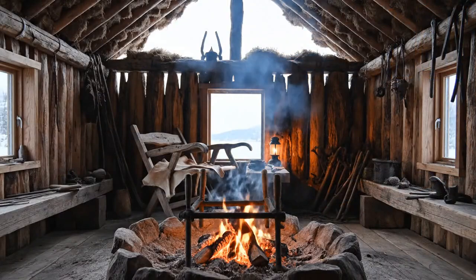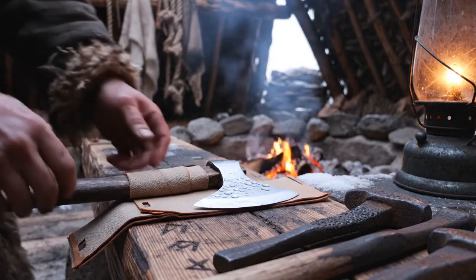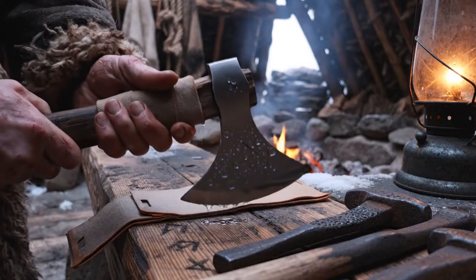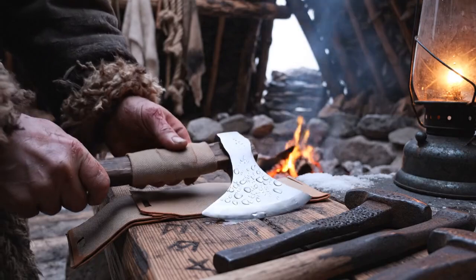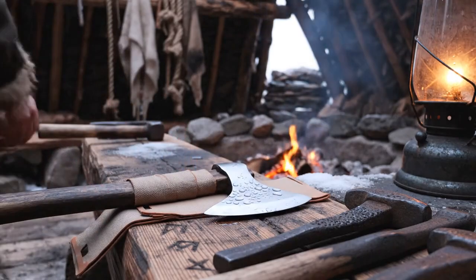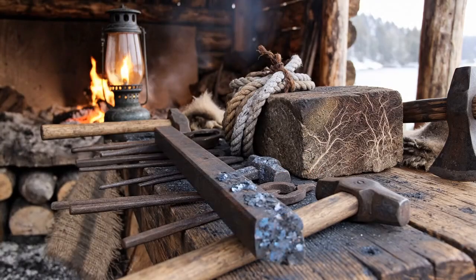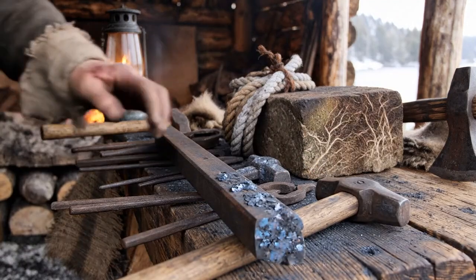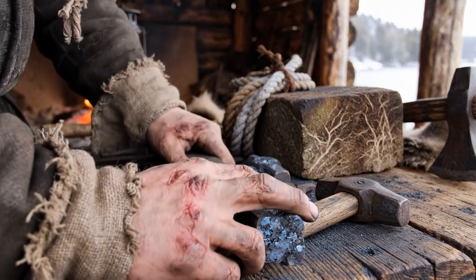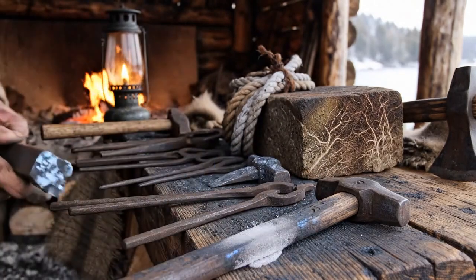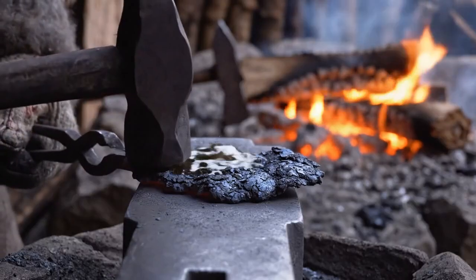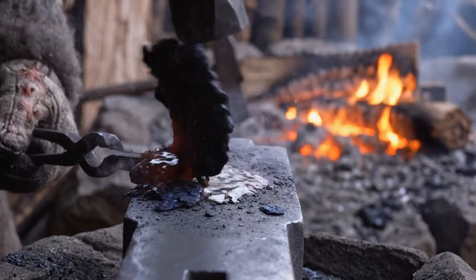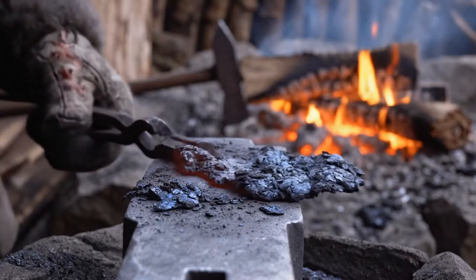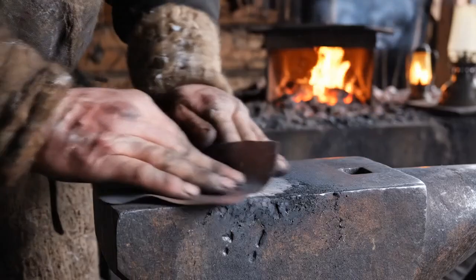The treatment bonds most effectively to iron and low-carbon steel. High-alloy modern steels, stainless steel being the clearest example, have a chromium oxide layer on their surface by design. That layer prevents rust on its own, which is why stainless steel is sold as stainless. But that same layer prevents the linseed oil from reaching bare iron to react with it. Applying this process to stainless steel produces almost no lasting result. Norse smiths did not encounter this problem because stainless steel did not exist.